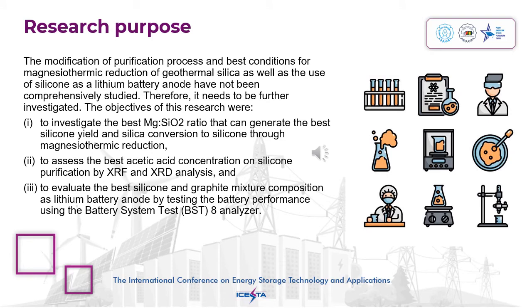The objectives of this research were, first, to investigate the best magnesium and silica ratio that can generate the best silicon yield and conversion of silica to silicon through magnesiothermic reduction; to assess the best acetic acid concentration on silicon purification by XRF and XRD analysis; and to evaluate the best silicon and graphite mixture composition as lithium battery anode by testing the battery performance using the BST-8 battery system test analyzer.